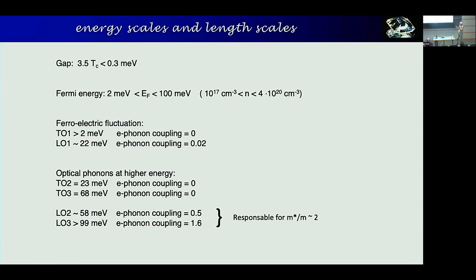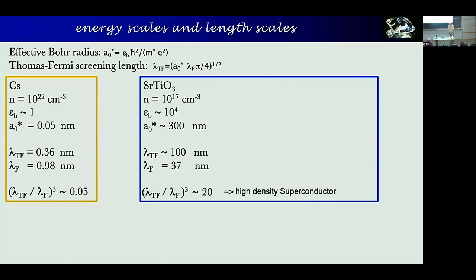And so for the lowest dopings you have really this hierarchy: the smallest thing is the gap, that's the range around the Fermi surface that is used for making a superconductor. Then you have the Fermi energy, which is at least 1 order of magnitude bigger than this value here, and then you get to the first phonons that you couple to, and that's yet another order of magnitude bigger. So especially for this part, you are in a strange regime, called the anti-adiabatic regime, where the usual treatment, Migdal-Eliashberg, wouldn't work.